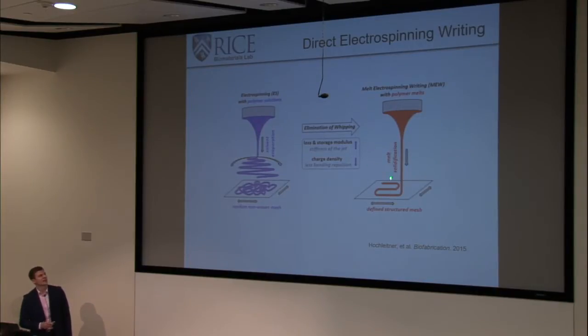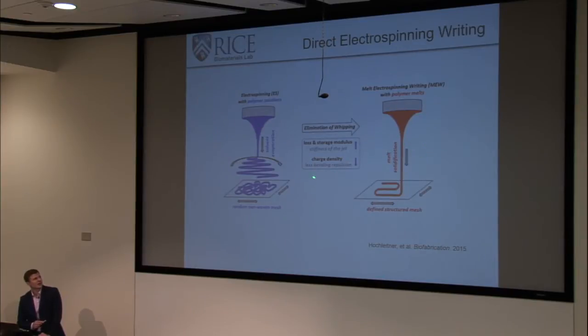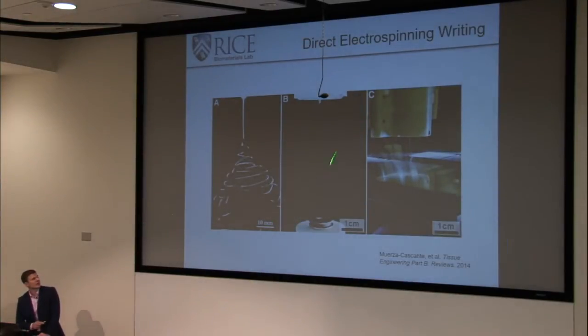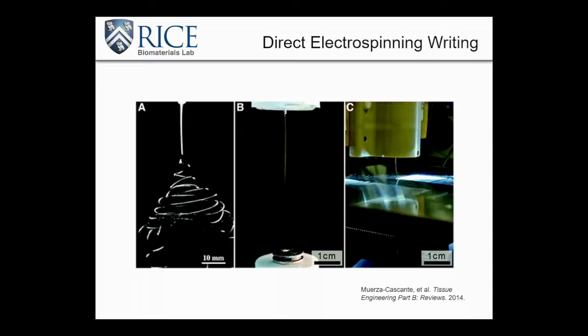In this case, because we don't have any solvent evaporation, we can actually produce a really uniform jet of material, and we can have these very nice deliberate designs that are very similar to the scaffolds that we're going to produce with our extrusion bioprinting methods. We don't have any charge density to work with since we don't have any solvent that's evaporating, which also reduces the bending repulsion, which we'll talk about in a little bit, at the interface between our collector and our material. So we have this really nice fine jet that comes down onto our collector, and that's exhibited here in these images. So here we have two different methods of the direct write electrospinning compared to what we might usually see with the traditional electrospinning that relies on a solvent or a polymer solution.